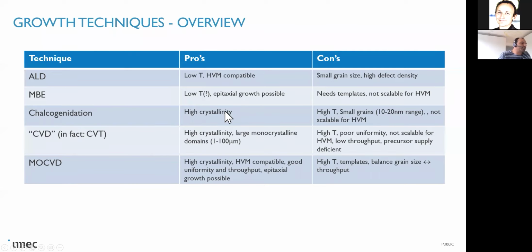Chalcogenidation, which is kind of an anneal in a chalcogenide environment, gives relatively good quality materials, but typically we have small grains, and it's very difficult to tune the grain orientation. Well, at least we didn't find it out, and also in the literature there are not so many people that manage to have, let's say, opportunities towards a single crystalline grain.